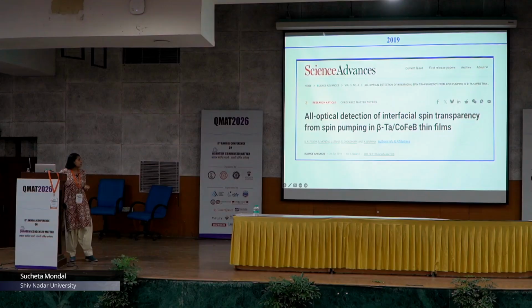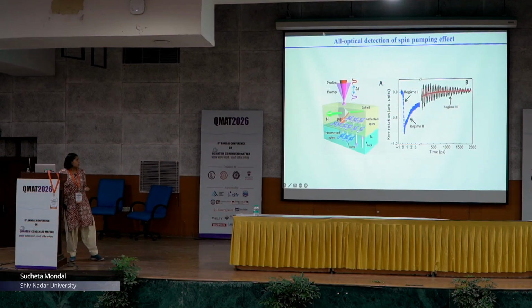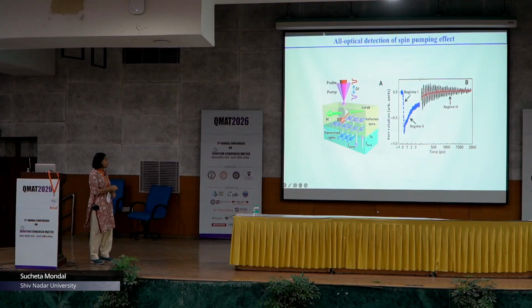Okay, so the next is about the spin pumping effect, which is the all-optical spin pumping effect. In that case, what happens? We do not really apply any charge current in this layer. What we are doing is simply exciting spin wave dynamics in this top layer by the pump-probe method, and then the precessing spin is transferring angular momentum to the adjacent tantalum layer.